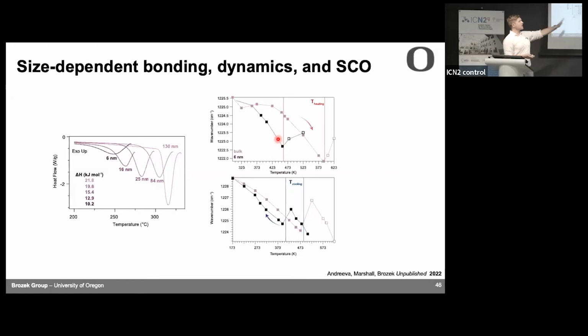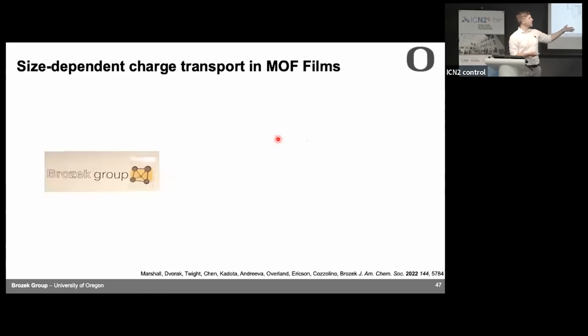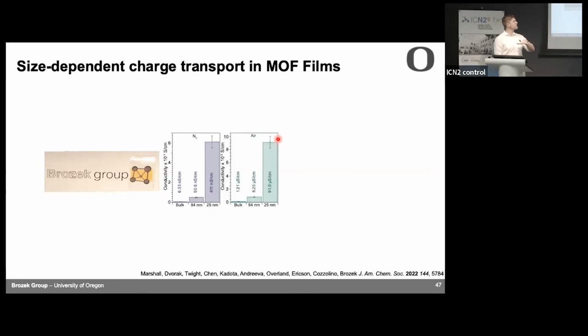So this was a nice sort of proof of concept, but we realized we have these really small particles, and now there's a lot that we should be able to do with them. And so much like has been done at this institute, we showed that we can make transparent thin films. So the yellow bit here is our transparent thin film from these particles on a glass slide. And because we can make these as thin films really easily, we can do 4-contact conductivity measurements.